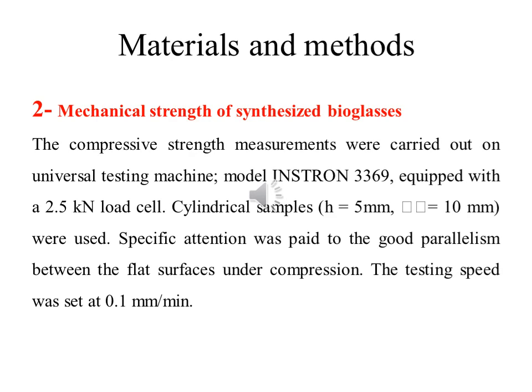For mechanical strength of the synthesized bioglasses, we use compressive strength measurements carried out on a universal testing machine, model Instron 3369, equipped with a 2.5 kN load cell, cylindrical sample, and specific attention was paid to the good parallelism between the flat surfaces under compression. The testing speed was set at 0.1 millimeter per minute.